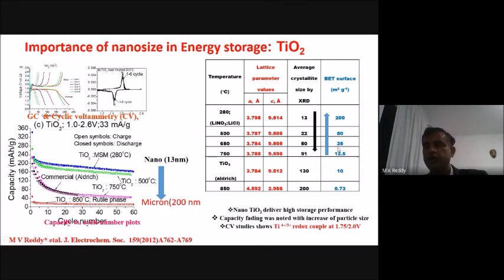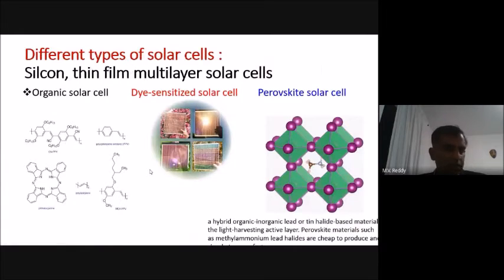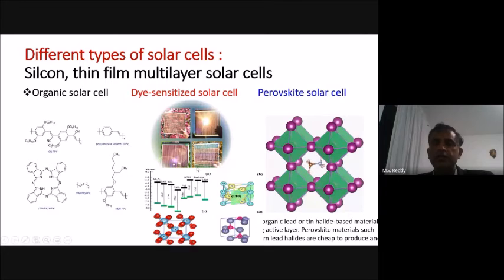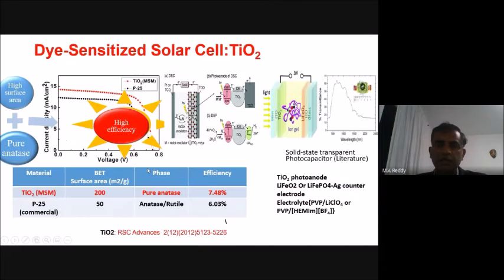At high temperature, we see a reduction of the surface area as well as an increase in the average crystallite size. Going from nano size to submicron size, you can see the crystallite size change, and overall nano size material seems to be good. People have already covered silicon type solar cells. Nano size TiO2 is well known, and DSSC has been demonstrated. This is one example of the use of high surface area material compared with commercial P25, although we get only a small improvement in efficiency.